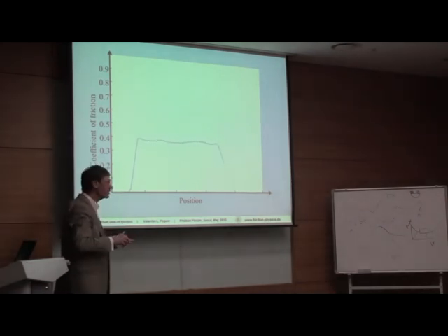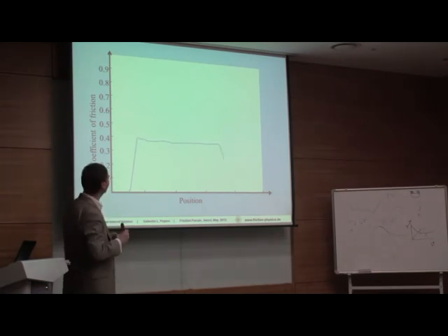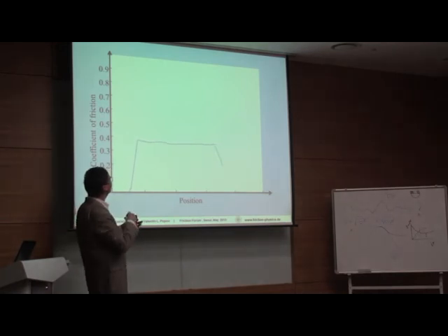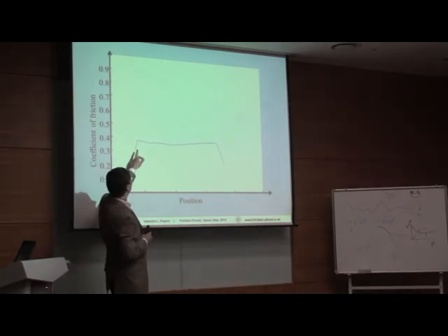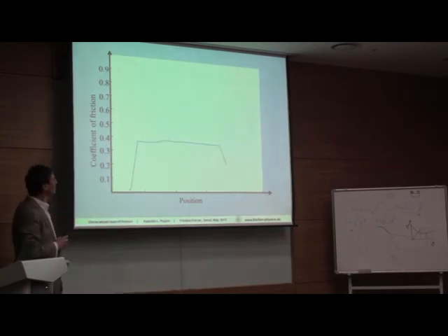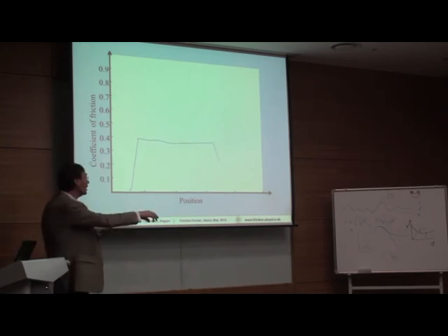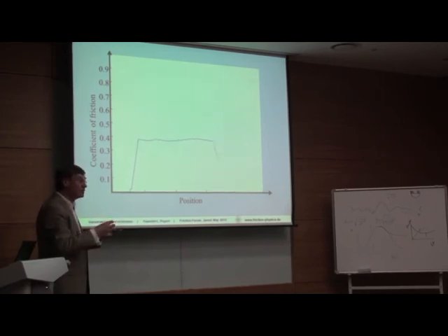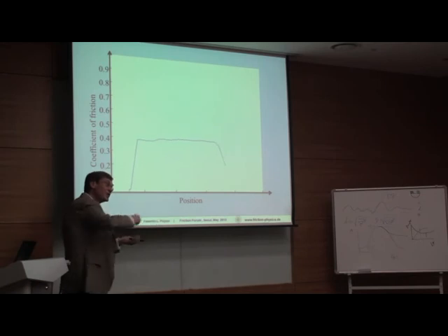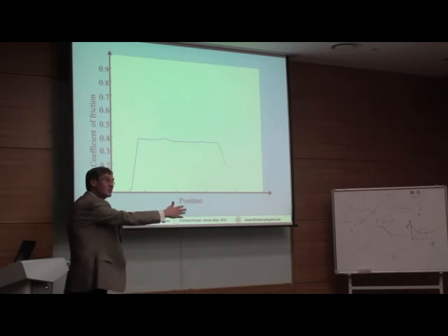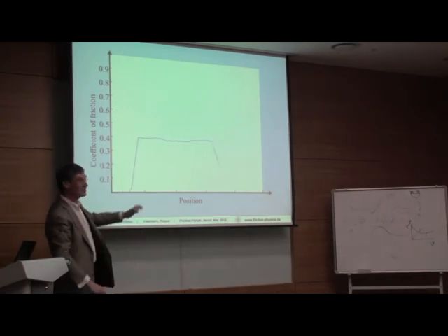This is how it's changing just with doing the experiment further and further. The frictional coefficient gets smaller, and then there is another interesting feature. After some time, it starts to develop some way from here. That's what we would call a conditioned surface. Yeah, it's conditioned, but after that, you have stationary behavior when some wave is going from one side to the other, but wave in the sense that you make 10 experiments, and if it develops, then you take the second 10 experiments, it is developing from one side to the other.